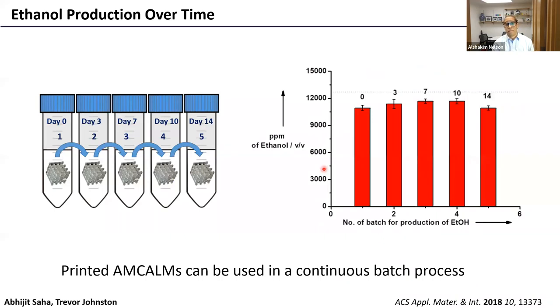But what's really cool about these structures is that they are reusable over time. And so if we take the printed construct and leave it in a solution of glucose for 2 or 3 days, and then take that construct out and put it into a fresh solution of glucose, then we see that the production of ethanol over time is constant. And we tracked this for a period of about 2 weeks where we saw this nearly constant production of ethanol. My student actually took this out to a period of 1 year, and still over that period of time, the production of ethanol was constant.